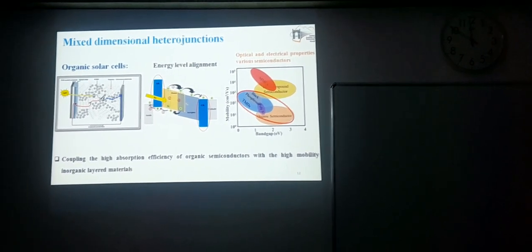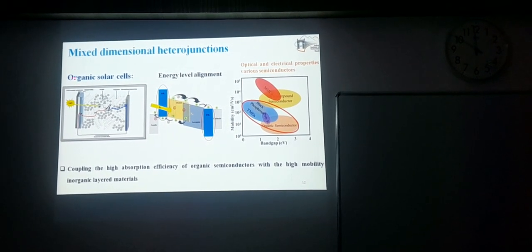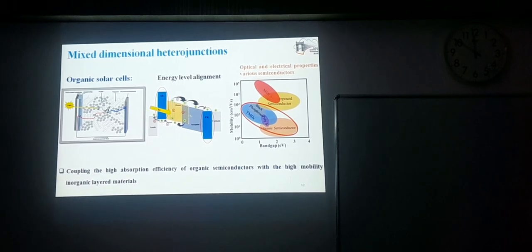So you may ask me why it's important. Just for an example, in the case of an organic solar cell, it has two different kinds of materials. So why is that? When sunlight falls on the active layer, one material absorbs the sunlight. When the sunlight falls on the semiconductor, you can generate a pair of excitons, bound by the electrostatic force between the positive and negative charge. And somehow you have to break these excitons at the interface, and you should collect these electrons and holes at opposite electrodes. And then you can use this photogenerated charge carrier.